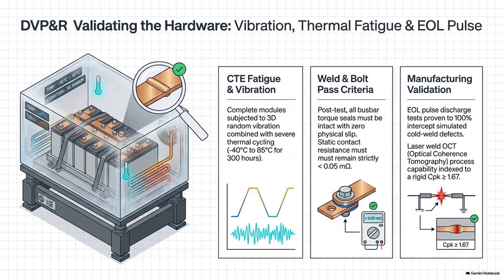And the passing criteria they are looking for is aggressively strict. The source document says the contact resistance must be less than 0.05 milliohms, 5 hundredths of a single milliohm. That's basically zero. That is essentially proving that the joint is electrically indistinguishable from a solid, uninterrupted block of copper. Exactly. If a laser weld suffered from that plasma keyhole collapse we talked about and formed a microscopic void, the 4-wire Kelvin measurement will detect that the resistance is, say, 0.08 milliohms. And it fails. And the pack will be flagged and rejected before it ever leaves the facility.